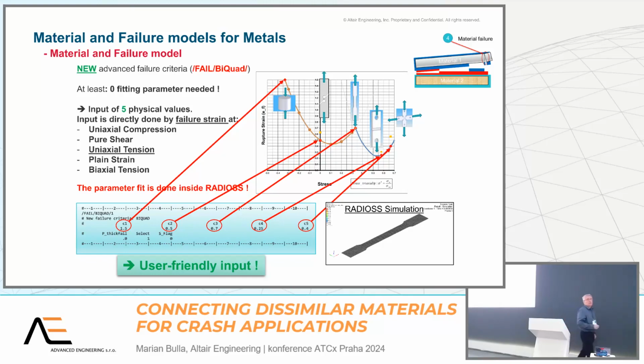And we simplified it. So we did it much simpler, where you can now forget the compression test, shear test, and plane strain and biaxial. Use only the most used tensile test. Keep these values at 0. And set a material flag here, which provides you an internal database for some material families, where we obtained the values from different research projects, and they already act very, very well. So you don't need to do these kinds of very enhanced tests. There is a small material database included in Radioss, which you can already use with predefined values. If you are happy with them, use it. They work